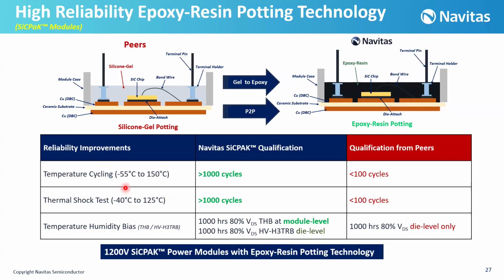Temperature cycling from minus 55 degrees C to 150 degrees C. Navitas with epoxy resin, more than 1,000 cycles, it passes. But if you look at the silicone gel, less than 100 cycles, it fails. Thermal shock test from minus 40 degrees C to 125 degrees C. Again, passes more than 1,000 cycles and fails less than 100 cycles. And the temperature humidity bias, high voltage H3TRB, this module passed at the module level, 80% VDS, 1,000 hours, and also at die level, 80%, 1,000 hours. But with the silicone gel technology, the module failed. We have only the die level for 1,000 hours, 80% VDS.